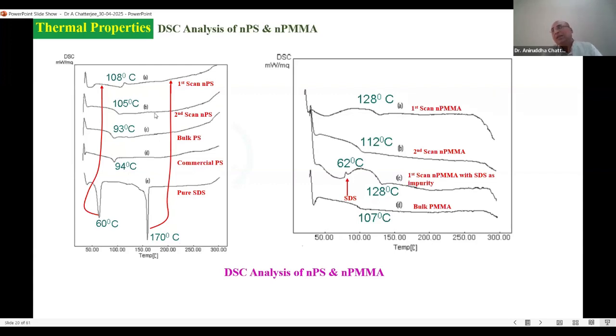So what is the reason behind that? The reason is that as the particle size decreases, surface energy increases. So due to the higher surface energy at the transition temperature, instead of absorbing heat, they are releasing heat. That's why the transition temperature is automatically increased from 94 or 93 to 108. Okay, the same thing is happening in polymethyl methacrylate nanoparticles. For bulk polymethyl methacrylate it is 107, whereas for polymethyl methacrylate nanoparticles it is 128.